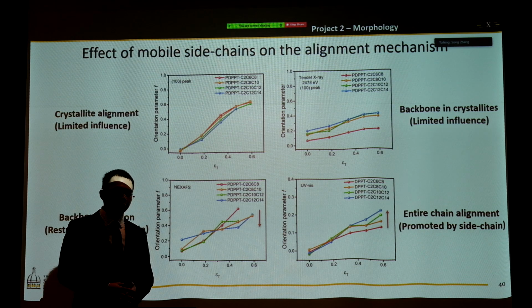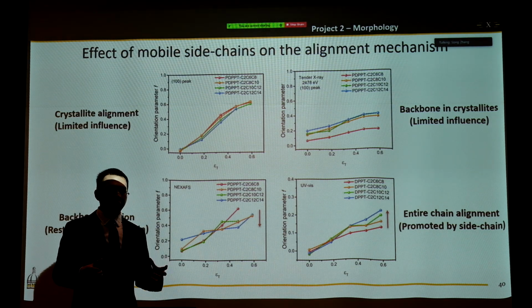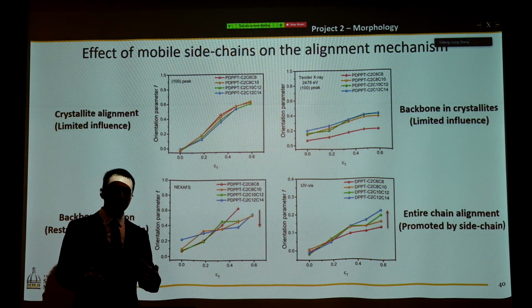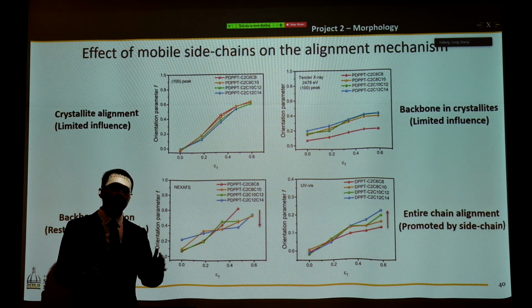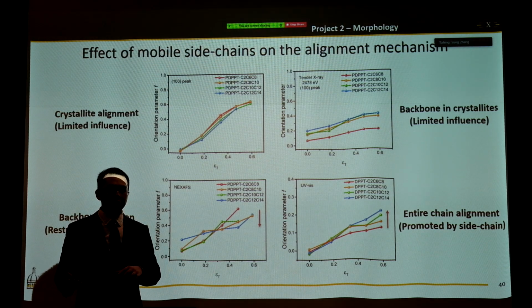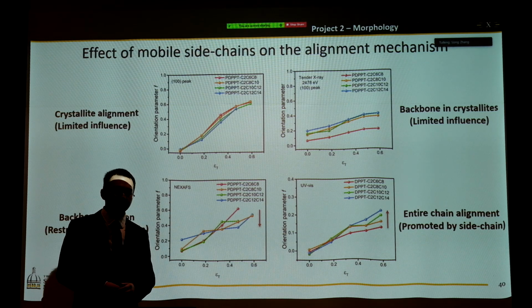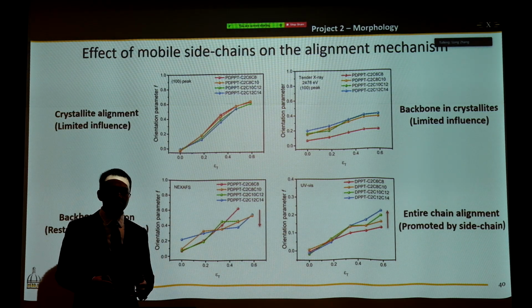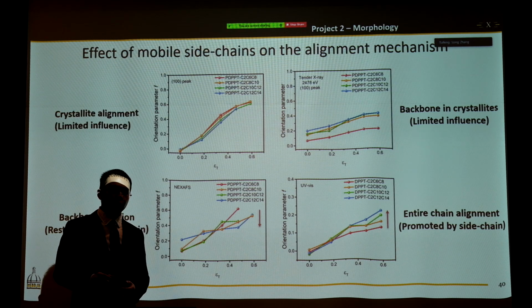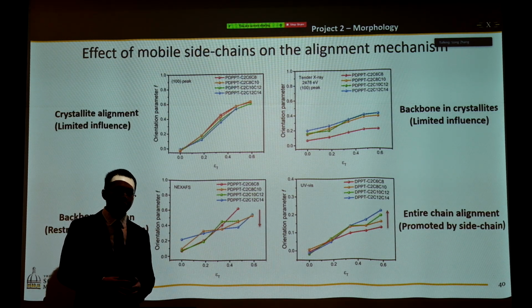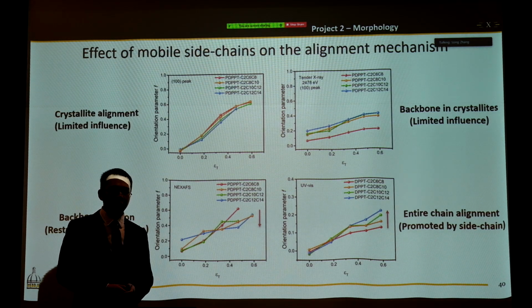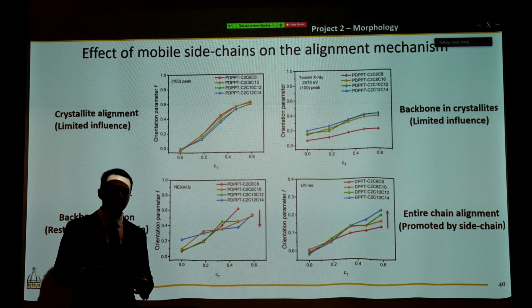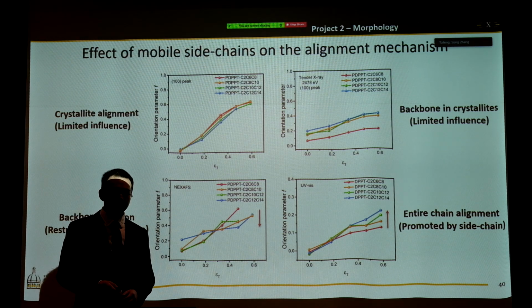From NEXAFS, we found that a larger size of the side chain is actually restricting the backbone from rotating. That can be explained because when the backbone is rotating, the large steric hindrance from larger side chains is stopping it from rotating further. And from UV-vis, we identified a little bit of increase in the degree of alignment for average polymer chains when we increase the side chain length. That could come from the more mobile polymer backbones for longer side chain polymers.